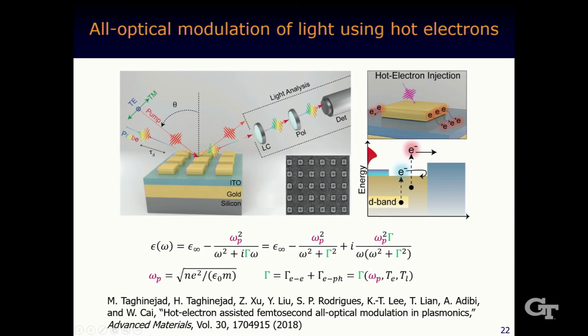And so when certain plasmonic resonance occurs, the hot electrons can be generated, and whether or not they escape into this ITO, the electron temperature and eventually phonon temperature can increase in the metallic particle, which can have an impact on the dielectric function of the metal. This can be seen from even the Drude model, where both the plasma frequency and the damping factor are related to the temperature of the electrons and the temperature of the phonons.